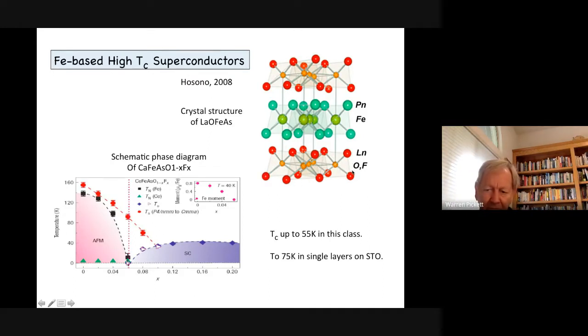Or sometimes you can put fluorine to take the place of some of the oxygens and change the properties somewhat. And it has a phase diagram. The phase diagram varies somewhat for all the different iron-based superconductors that have been discovered, but there's an antiferromagnetic order in most of them before it's doped, and then there's a superconducting dome, as it's called here, and so forth. And there's a structural transition in this material also. So this is Tc up to 55 Kelvin.